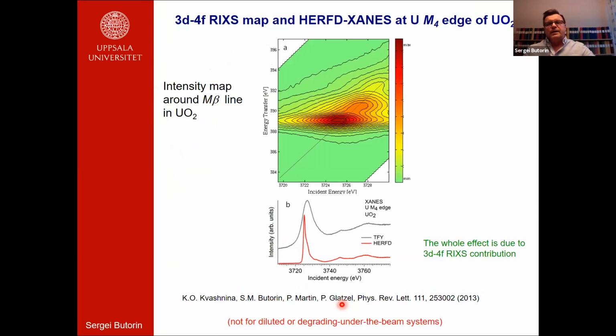Of course, the right way to do it is to measure the whole 3d4f RIXS map, as shown here, an intensity map around the M beta line in UO2, shown on the incident energy axis and the energy transfer axis. Then one can make a diagonal cut through the maximum of the intensity and obtain the HERFD spectrum. One can make different cuts and obtain different information. And here we see the improvement in the HERFD spectrum compared to conventional XANES. But you should realize that the whole effect of this sharpening comes from the 3d4f RIXS contribution.